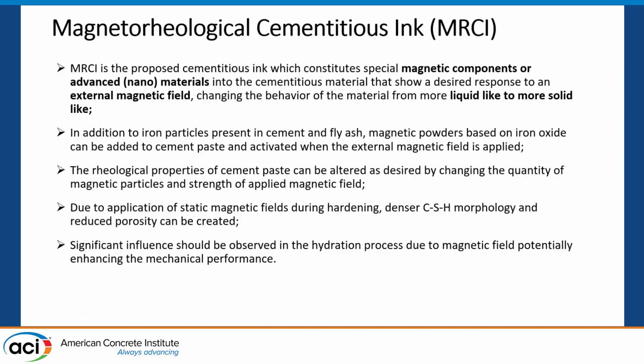Well, why am I talking about fly ash? Because fly ash is magnetic by itself as well, especially type F fly ash, which has considerable quantities of iron oxide. And here the idea is to, again, incorporate magnetic components, including nanomaterials, which can help with viscosity control, and make the material respond to an external magnetic field. And again, the switch from liquid to solid is the desired response which we target here.